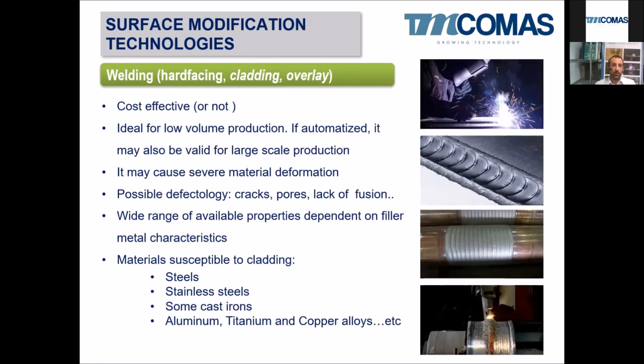Well, the next one is welding. Welding is a very, very known technique. I will talk about cladding. So not joining, not welding two parts together, but welding onto a surface of the part to improve the properties of the part. So it's hard facing when this welding is for wear protection. Cladding is more or less a generic word for this welding of coatings for protection. And overlay is more or less when we apply a welding layer to protect the base material against corrosion. So hard facing for wear, overlay for corrosion, and cladding is a general term.